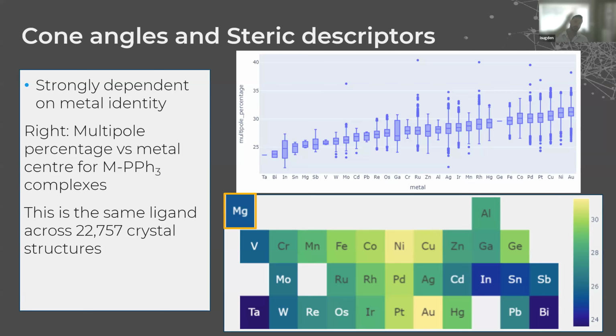And you can see going across these transition metals, you get a column where there is largest multipole percentage for nickel and gold, and then at the extreme edges of the transition metal section of the periodic table, you have much lower percentages. And as I was indicating earlier, that's due to the different electronic orbitals at the metals in each of these centers. So this is the same ligand across 22,000 or nearly 23,000 crystal structures. So it's a reasonable data set to start making these assignments with. But you can see there is quite a lot of spread of results, certainly for silver and ruthenium.